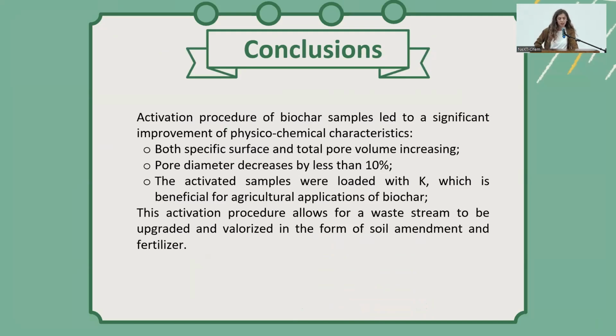So we concluded that our activation procedure was beneficial if we talk about the physical chemical characteristics of biochar. We saw that both specific surface and total pore volume increased, while pore diameter decreased by less than 10%. But this shows us that the activation method that we used did not collapse our pores. So in the end, we obtained some activated samples loaded with potassium, which is beneficial for agriculture application of biochar. So this procedure allows us to upgrade a waste stream in the form of soil amendment and fertilizer.